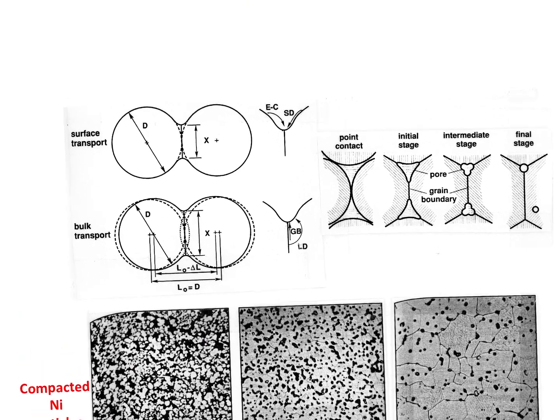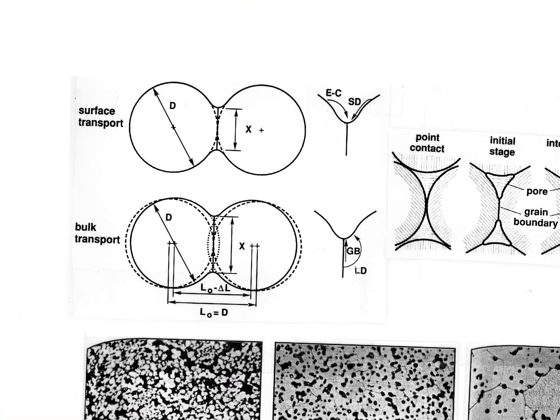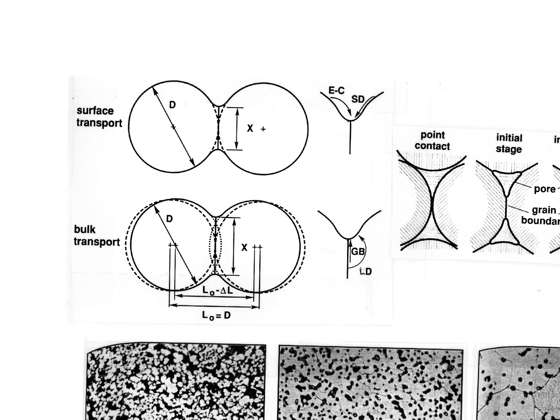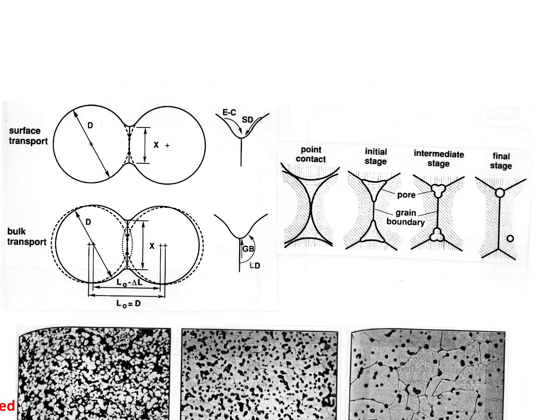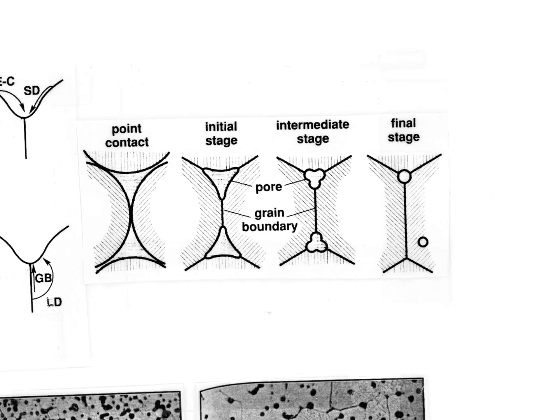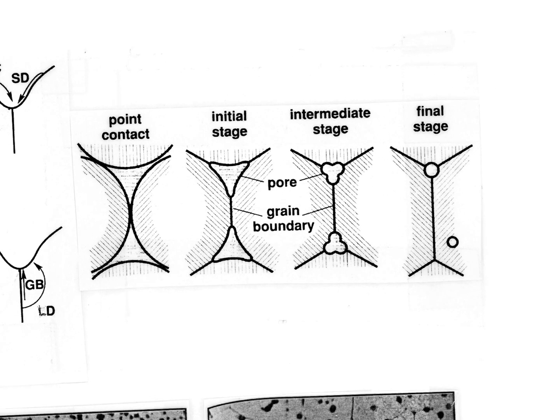And then we talk about a couple of other things. And so we have this surface diffusion and grain boundary diffusion and lattice diffusion, all of which are going to the same place, moving atoms around. And we have, getting a little more advanced here, the initial point contact where they first touch, and it gets rid of that point contact as quickly as possible to cause a grain boundary, which replaces gamma sub s with gamma GB. The system likes that. All right.